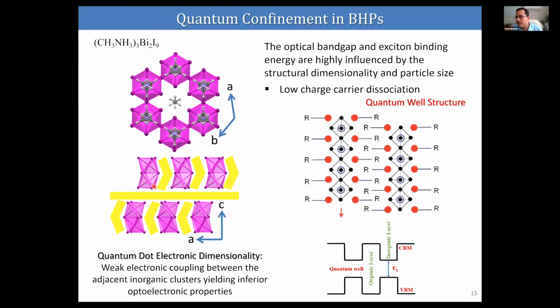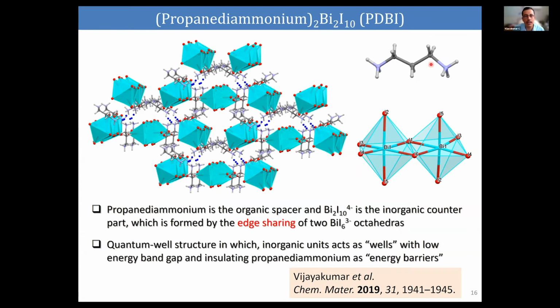So what about making quantum well structures? If you cannot get good properties from the quantum dot structures, go to the quantum well structures, because that is much better than the quantum dot structures. So we try to avoid the methyl ammonium cation, and instead of that, we used a dication, a propanediammonium cation. So we can use less number of organic cations, because here one organic cation has two charges. So you statistically need half of the organic cation required, and we synthesized the bismuth halide material like this.